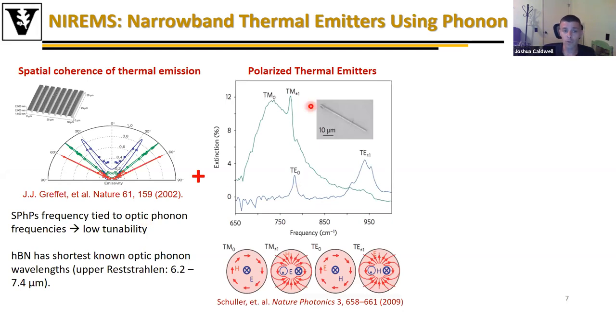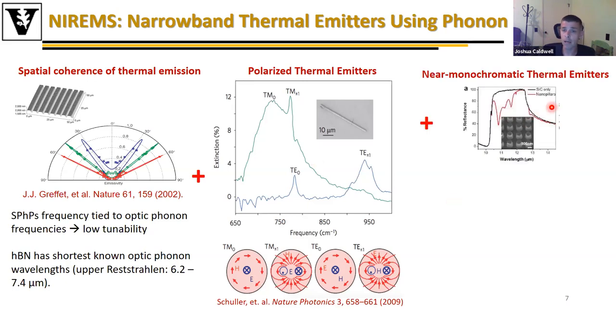Later on, there was some work from Mark Brongersma's group with John Schuller as the lead author, where they used micron scale microwhiskers of silicon carbide. And they were able to demonstrate that the thermal emission from the localized resonances in these structures gives rise to polarized far field thermal emission. So the polarization of the polaritonic mode actually is retained into the far field, meaning you can realize a polarized light source doing this.